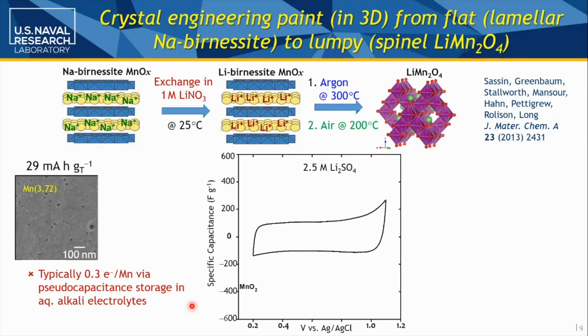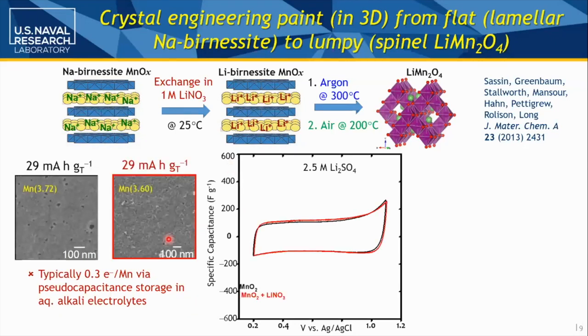So Megan exchanged the sodium in the inner layers for lithium, just an aqueous soak in lithium nitrate. Now we've got a lithiated system with essentially the same footprint, because it really should be 29 milliamp hours per gram total electrode. We've lowered the amount of manganese 4 in the system a bit with the lithium, but you can see it's giving you roughly the same performance in this lithium sulfate aqueous electrolyte.